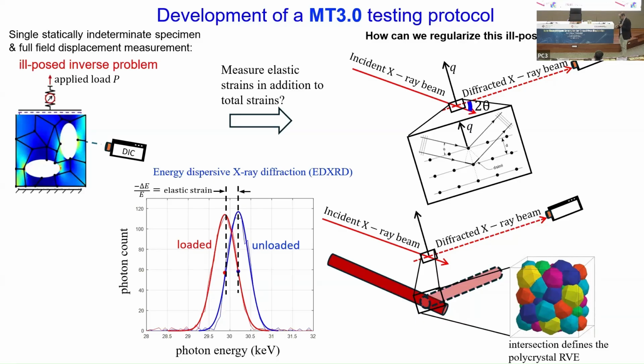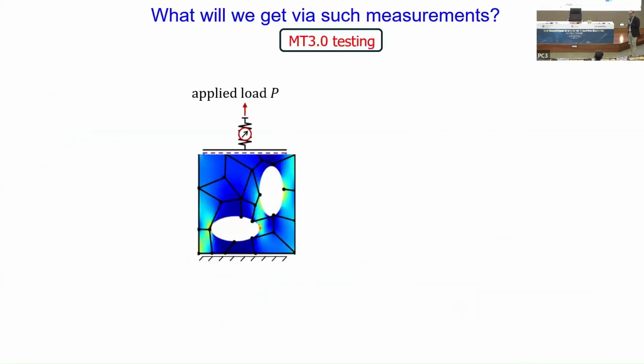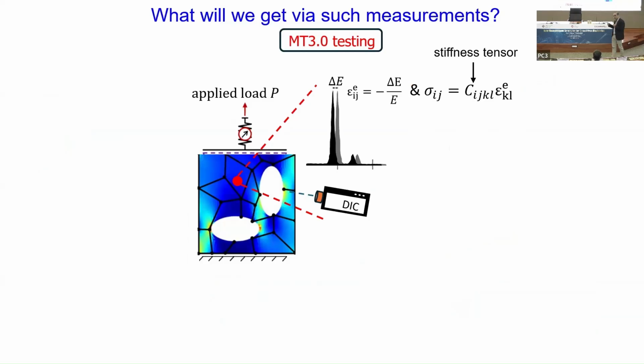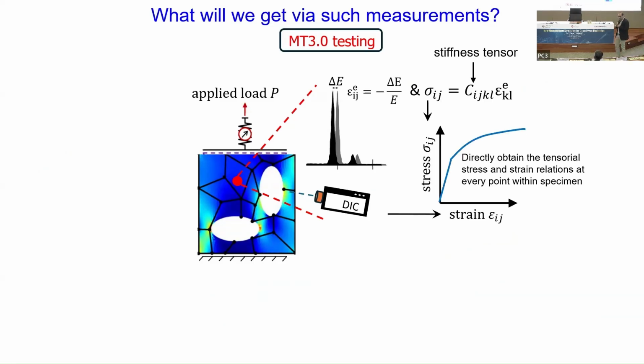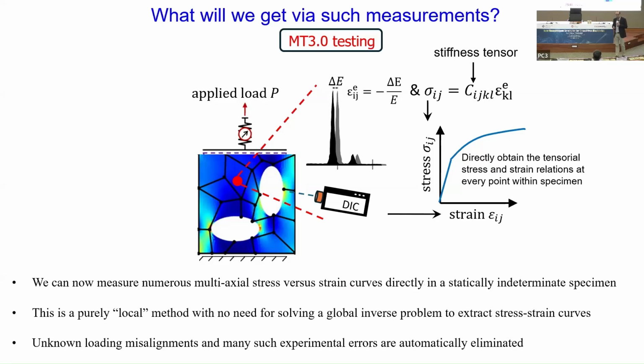So now you've got yourself this rather interesting measurement tool, where if you do this kind of a test, you not only are going to be measuring these strains using something called digital image correlation or something like that, but you'll also be measuring the elastic strains. So the total strains as well as the elastic strains. That means you know the stress and you know the total strains. And that means that as you start loading this specimen, at every point within this specimen, for example this particular point here, you'll get a multi-axial stress strain curve. At another point here, you'll get another multi-axial stress strain curve. At another point here, you'll get another multi-axial stress strain curve, with solving no inverse problem at all. So with one test, you're going to get lots of these different multi-axial stress strain curves. And that's how you basically have reduced the problem to doing it in one measurement. One test is going to give you all that data. So that's what we are basically saying here.